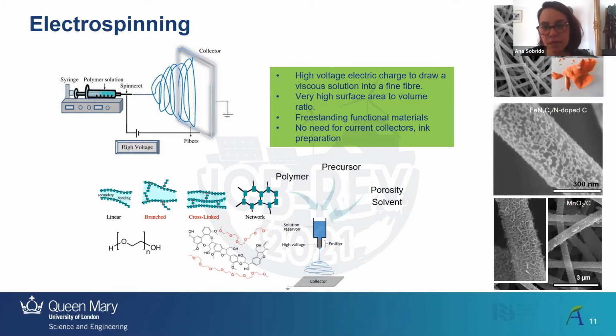Then here we have some nitrogen doped carbon fibers with some iron and nitrogen on the surface, which is like an oxygen reaction catalyst. And then here we have fibers that have carbon, but then all these flakes are manganese oxide, and this one finds applications in supercapacitors. So as you can see, completely different textures and compositions that we can achieve with this technique.